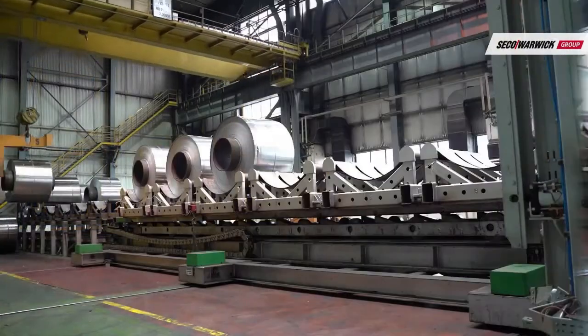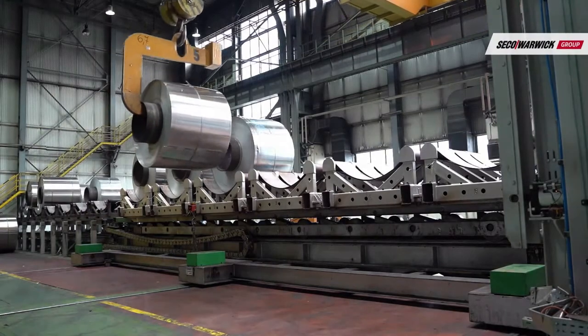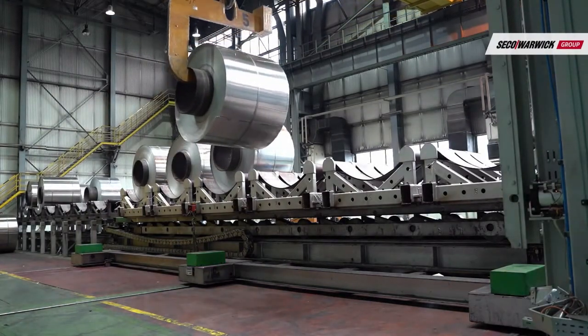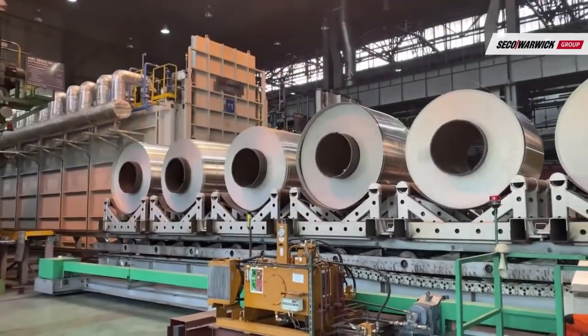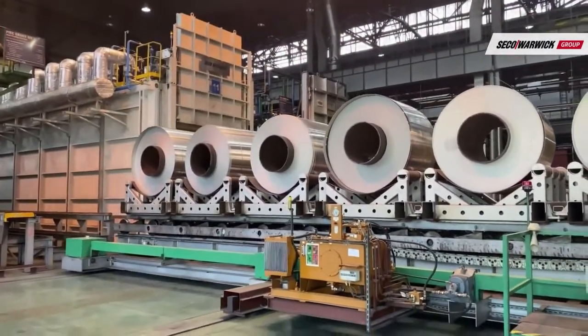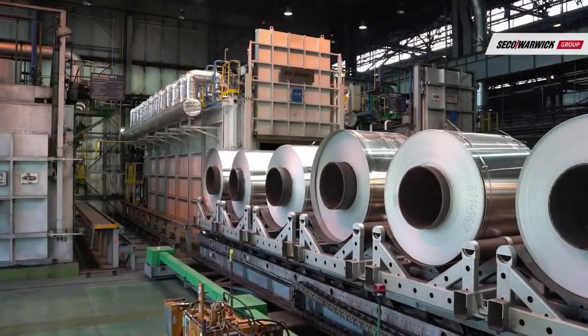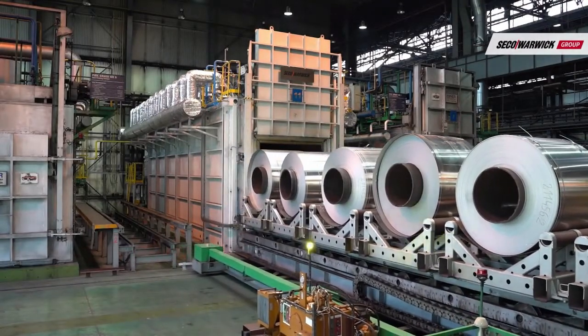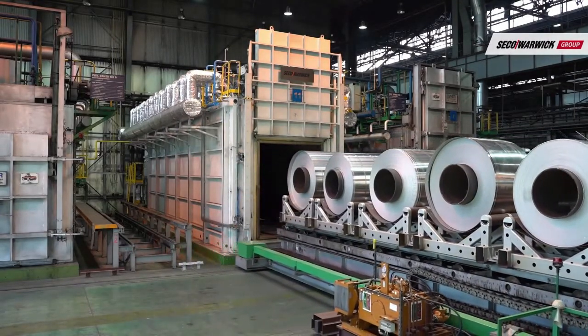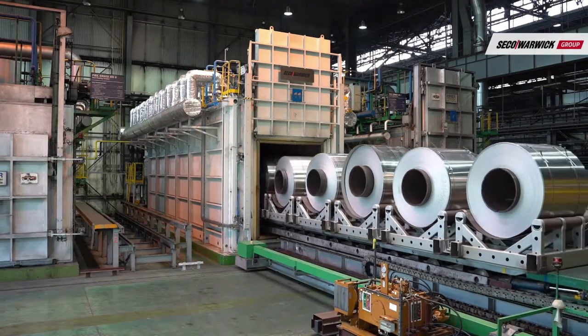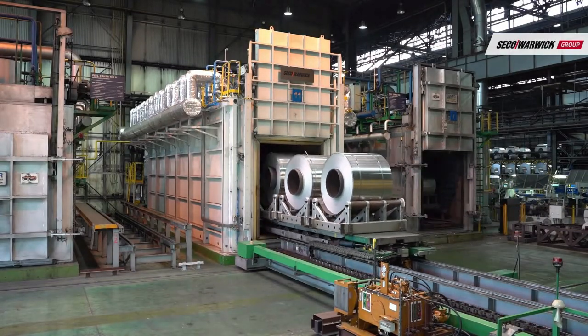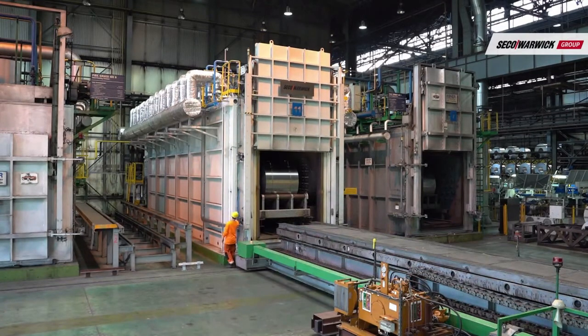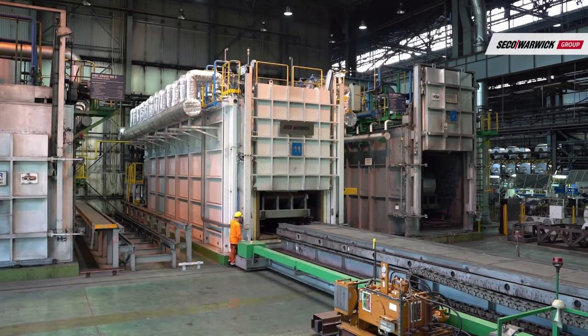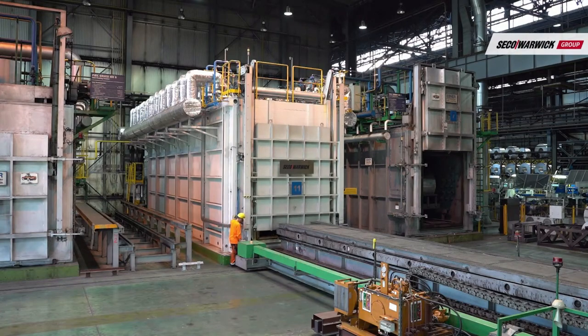Stress relief annealing is used when the material has lost its ability to deform due to rolling and the process has not yet been completed. As a result of stress relief annealing, a gradual, continuous disappearance of the deformation of the crystal lattice caused by the strain occurs. As a result of recrystallization annealing, new grains are formed with an undistorted crystal lattice, as a result of which the tensile strength of the material reaches the minimum value and the elongation the maximum one. Full recrystallization of the material completely removes the effects of cold work.